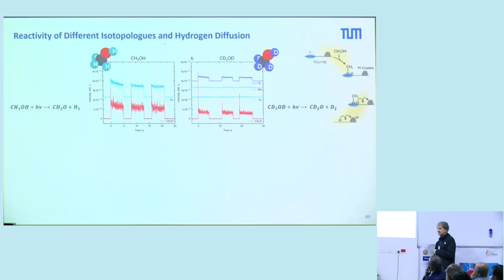Now, what other steps can be important? We see that also the mobility of the hydrogen to the cluster can be important. And for this, we studied different isotopologues. That means you see here the reactivity of methanol with only hydrogen, and here with deuterium. And you see a decrease in the reactivity if you use the deuterated methanol. That means this diffusion of hydrogen will also be relevant in determining the reactivity of this oxidation.